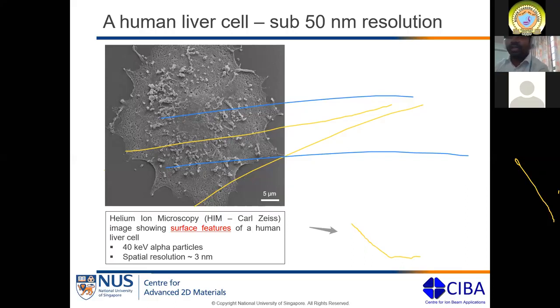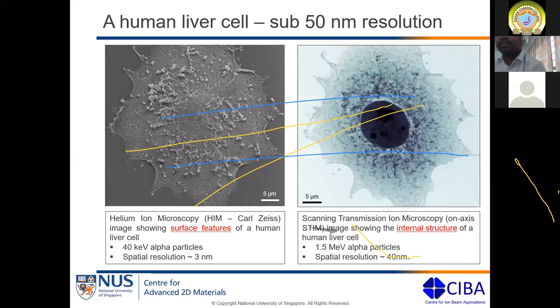But if you look at the STIM imaging of the same cell, you can actually figure out where the nucleus is, and inside the nucleus you can see finer details or some black spots which were missing from the helium ion microscopy. So it clearly shows that helium microscopy is good when you are looking at the surface of the material, while if you want to see the finer details in your cell or sample, you better look at it with STIM mode.